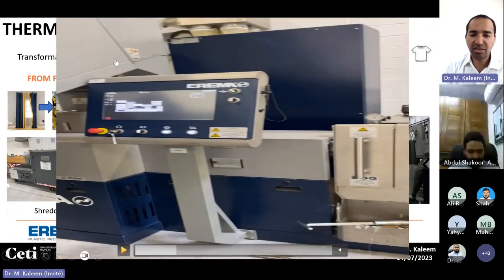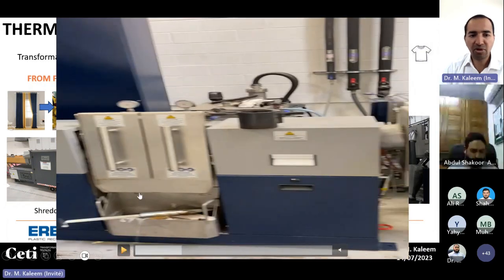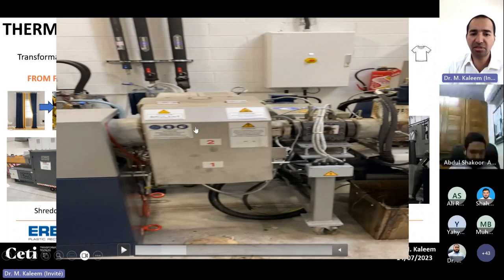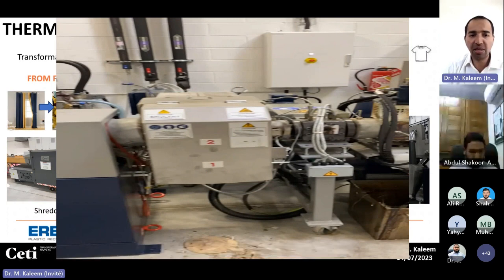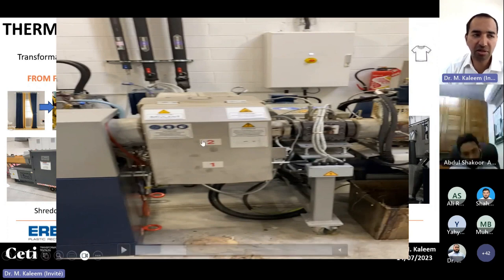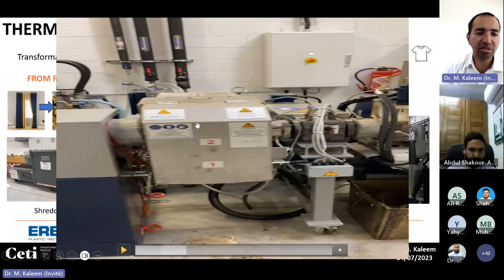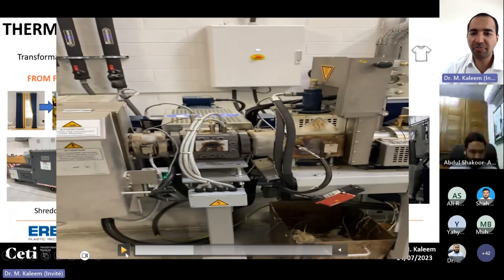And then this is the extruder. This feedstock feeds the extruder gradually, and when we have a stable process, we set a specific feeding rate from here. Then you have a vacuum system to remove all the humidity from the feedstock. And then here you have a filtration system. In this line, we have a backflush filtration system, which means there are two filters at the same time, a two-piston type filtration system. That means you don't have to stop the process, so your melt stream is filtered during processing. If the contamination is high, you have to change the filters depending on the level of contamination.